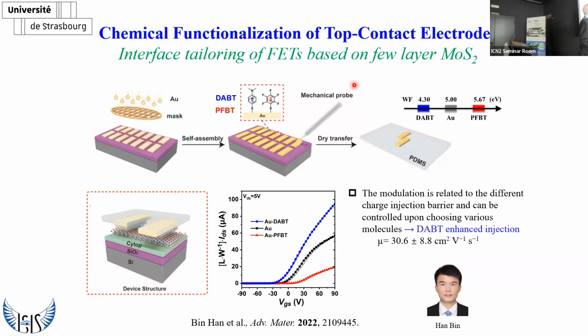Anyways, when he used two equally functionalized electrodes, so symmetrically functionalized electrodes, he can optimize the charge injection in the transistor when he uses the DABT that lowers the work function of the gold electrode. And so he reached a mobility of about 30 cm² per volt per second, compared with pure gold, which is about half of this, about 15, and below 10, in red, when the unfavorable work function characterizes the gold electrode, so when the perfluorinated molecule is functionalized.